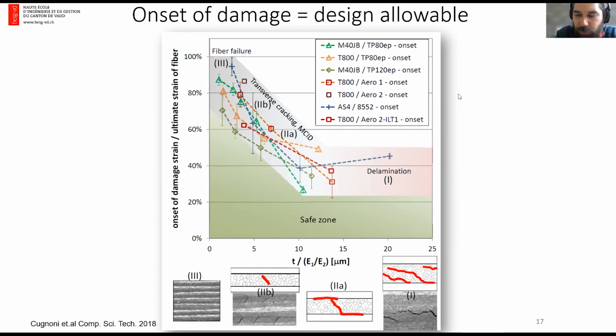But from what I know, the failure mode of thermoplastic composites is that they are much more sensitive to fiber matrix debonding than thermosets. It's a guess, so it's not certain, but I think transverse cracking will happen anyway because of fiber matrix debonding in thermoplastic composites, while in thermosets transverse cracking happens through plastic strain accumulation in the plastic band, so localization of plasticity. So it might be a different mechanism, but it all depends on the fiber matrix interface toughness and strength.